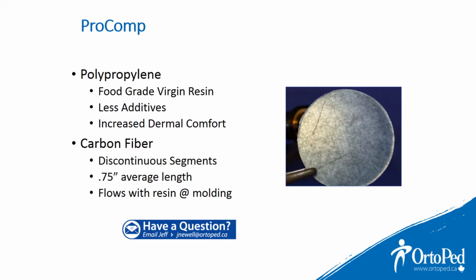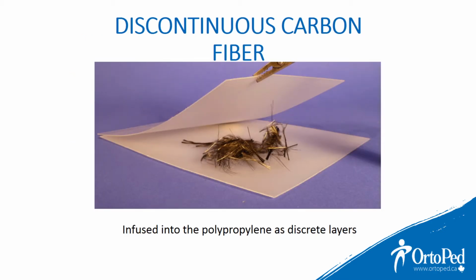ProComp is the combination of two materials, polypropylene and carbon fiber. The polypropylene is food-grade virgin resin, which has less additives, increased dermal comfort, less chance of allergic reaction. The carbon fiber is discontinuous segments, 3/4 of an inch average in length, and flows with resin during the molding process. Here we can see multi-directional carbon fiber infused between two layers of polypropylene.